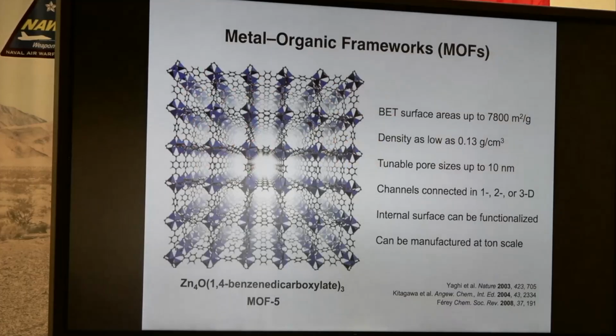So just to introduce metal organic frameworks, these are network solids built up of organic linkers connecting metal centers into a 3D porous architecture. These materials can have the highest surface areas of any known materials. These can be up near 8,000 meters squared per gram. And this is important, two things that are important about MOFs.